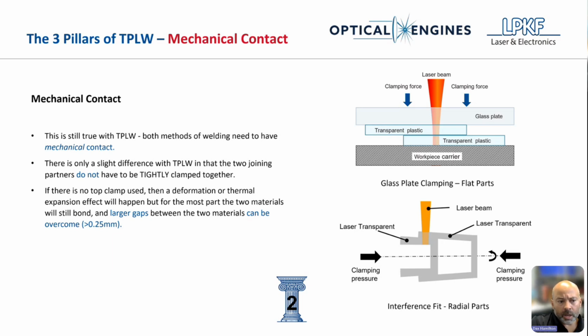And one thing that I do point out, the parts don't have to be tightly clamped together like we recommend for through transmission welding. That is because of thermal expansion, because of volumetric absorption. So everywhere the laser is shining, basically it's heating up, thermally expanding, and in some cases can close those gaps. So it is something that we have going for us in 2 micron welding. Should point out too, if you just lay the 2 pieces of plastic flat and you shine the laser through it without clamping, they will weld in a lot of cases, but you'll see this raised bubble, this thermally expanded portion of your plastic. So just something to keep in mind.